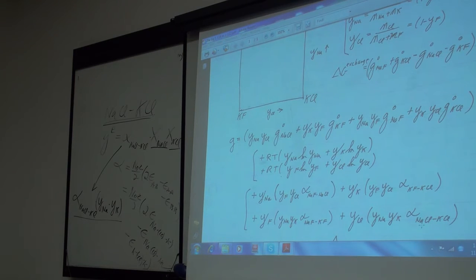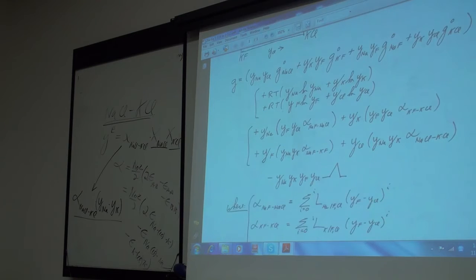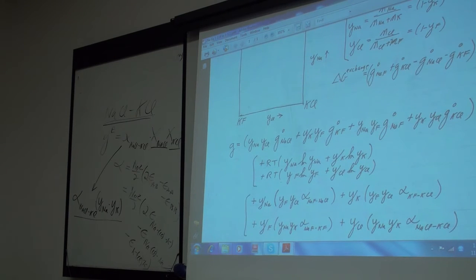Then we have second nearest neighbor interaction between the negative ions, between the ions. So these are the second nearest neighbor terms along here between the positive ions. These are the second nearest neighbor terms between the negative ions. So if we're down in this binary here where you have only potassium, this is the second nearest neighbor interactions between fluorine and chlorine when the other sublattice is occupied only by potassium, and up here is the same thing when the other sublattice is occupied only by sodium, and so we vary linearly between the two.